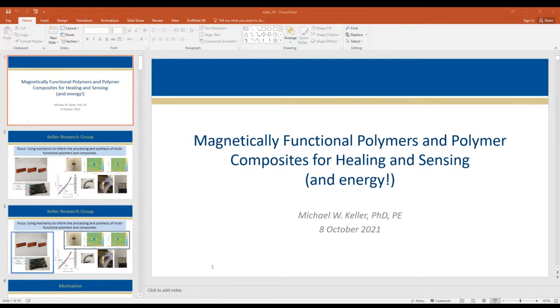The way that we did it was we created channels through a really low-tech process. So here's my carbon fiber. Here are some Teflon-coated wires. We basically laid the thing up, and then we yanked the wires out of it, right? And in such, we created a vasculature, right? So now I have channels like blood vessels that are sitting here, and we can then flow material in.